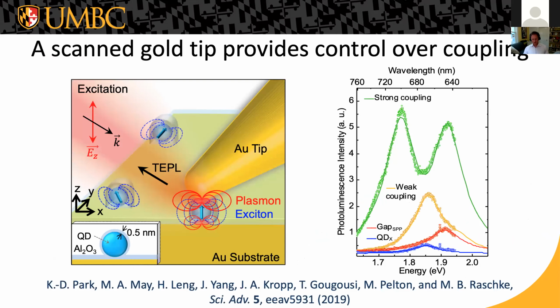So to make things a little more controlled, or I should say, a lot more controlled, we worked with Marcus Raschke at the University of Colorado and essentially replaced the gold particle with a scanning probe tip, a near-field scanning optical microscope tip, also made out of gold and tapered down to a nanometer scale point at its end. So this tip now we can scan around the surface, find the quantum dot, and position it directly on top of the quantum dot, and do this over and over again with different quantum dots on the sample.